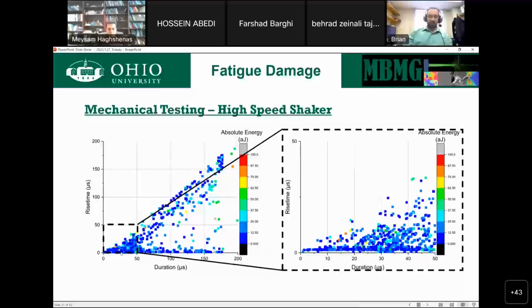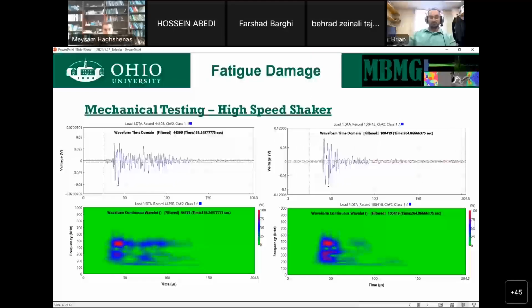This low corner here is the area where you get all the dots at the beginning of your experiment. After a period of time, they shift away from this location and start to fill up other areas. And so you can very simply mark a transition in damage mechanisms just by where you're getting your dots. It's a quite powerful method that is actually fairly simple, which is nice.